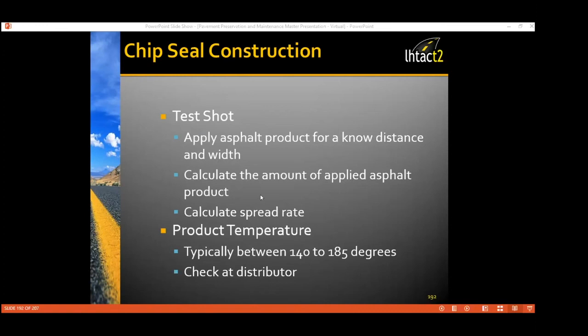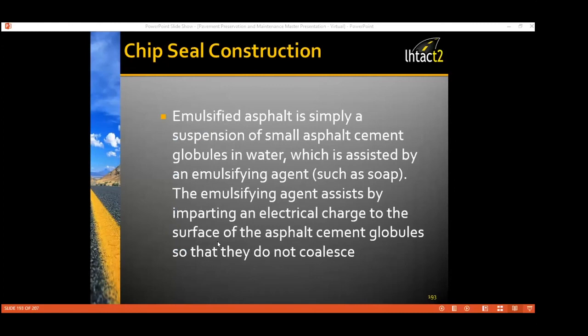Product temperature is typically between 140 and 185 degrees. So this emulsified asphalt shows up on the job site in a great big huge trailer from Asphalt City, and it typically is running a temperature of, to begin with, about 185, 190, and it'll stay hot for quite a while in the truck. So you want to check the temperature, not at the big truck that hauled the asphalt in, but at the distributor and how it's coming out. That's crucial. Make sure you've got material that's hot enough.